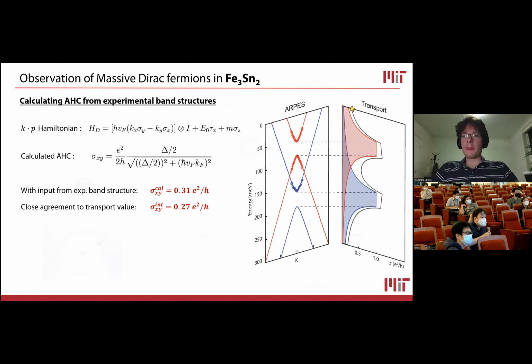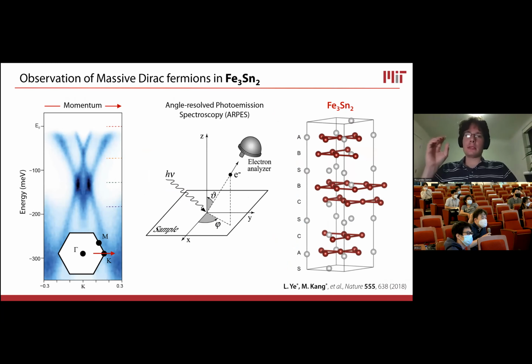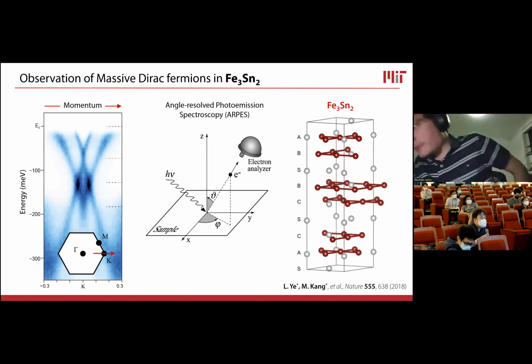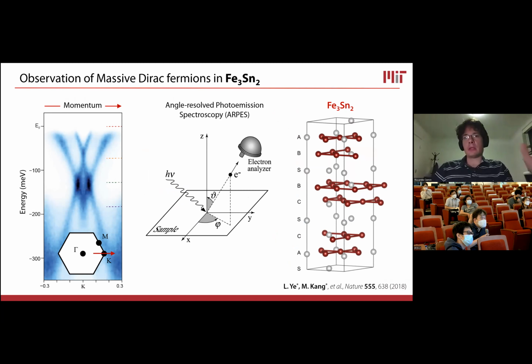Yes, great question. So, right. In principle, if we could look at single magnetic domains in this Fe3Sn2, then we would expect to have a helical edge state around it. This is a weak 3D TI system essentially. So each Kagome layer is in the quantum anomalous Hall limit effectively. And so in principle one would expect the signature of these helical edge states, but it has not been observed in this particular material, and it would probably require some probe with high spatial resolution, because this material has a very complex domain structure, and so one really has to look at edge states at the boundary of domains in the system.